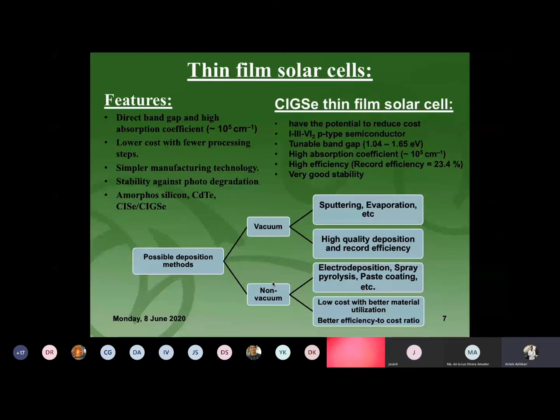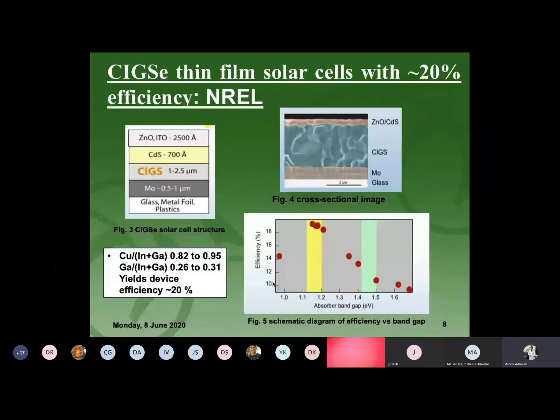Among the different semiconductor materials, CIGSe thin film is promising as an alternative to silicon-based solar cells because of its stability, reliability, and high record efficiency of 23.4%. It also has the advantage of a tunable band gap, 1.04 to 1.65 electron volt. The available deposition methods, depending on material quality and fabrication cost, are divided into vacuum-based and non-vacuum-based methods. Here I'm mentioning one example of a CIGSe thin film solar cell with around 20% efficiency by NREL.